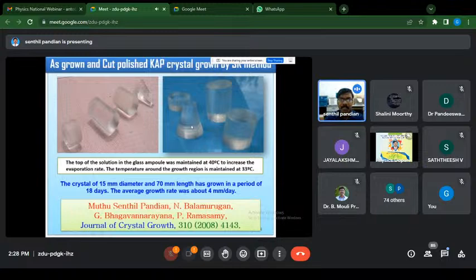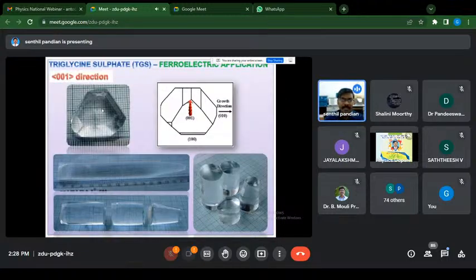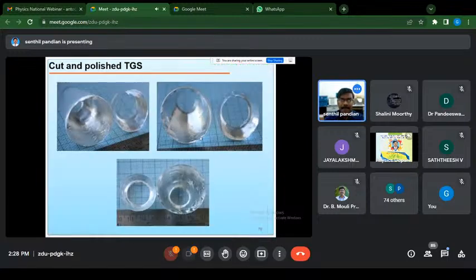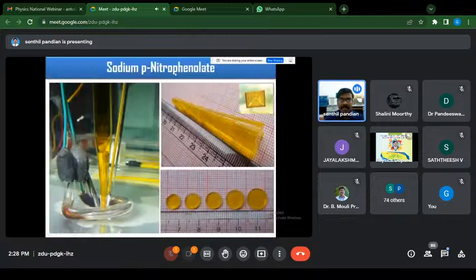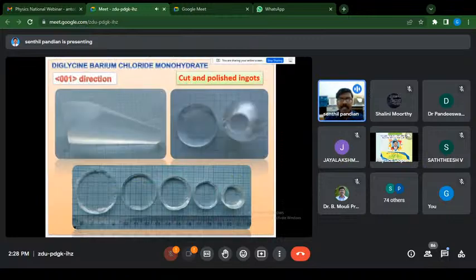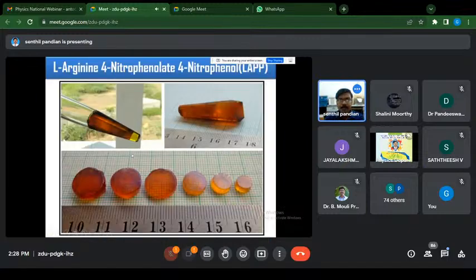And this is the KAP, potassium acid phthalate single crystal grown by this SR method. And this is the ferroelectric TGS crystal along its c direction. And this is the cut and polished TGS crystal. And this is a sodium para-nitrophenolate single crystal grown by this conventional method. And this is grown by this SR method. And these are the cut and polished wafers. And this is the diglycine barium chloride monohydrate single crystal as grown. And these are the cut and polished wafers.